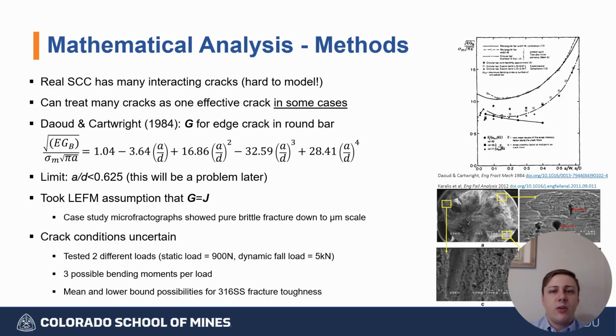Our analysis attempted to determine the critical crack length of failure for the stress corrosion cracking damaged bolts. Our methodology for this included the assumption that the network of many cracks characteristic of stress corrosion cracking could be treated as one singular edge crack of a single effective length. We then followed a form of the strain energy release rate developed by Daoud and Cartwright for this loading geometry, and made several assumptions about the possible range of load conditions at failure, including several different bending moments and several different load cases, including a static and a dynamic or a falling load case.